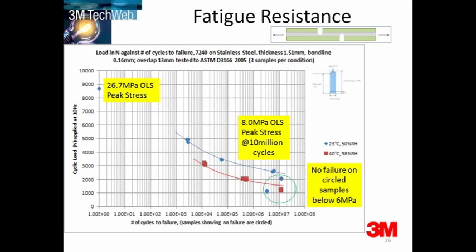Cyclic loading — fatigue. Fatigue is the progressive structural damage that occurs to a material under repeated or cyclic loading. If the stresses on the cured structural adhesive are above a certain threshold value, microscopic cracks can begin to form. And these can reach a critical size where sudden fracture will occur.